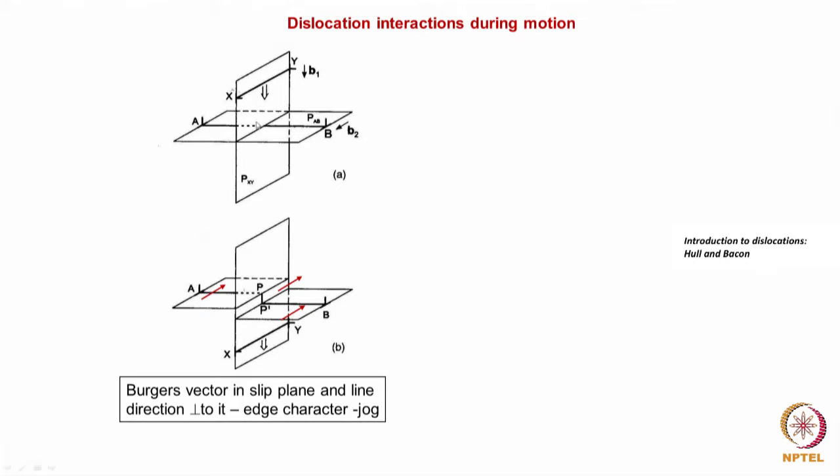because that has to move the atoms on this plane. When this dislocation passes through this region, it has to move all the atoms in this plane by that vector, it should shift it. So the dislocation line would have shifted here. So this is how the dislocation looks now. A step is created, and the step creation means that there is an increase in the length of the dislocation. This way, as the dislocations interact, the length of the dislocations can increase. So this also leads to multiplication of dislocations. Let us look at this particular one.